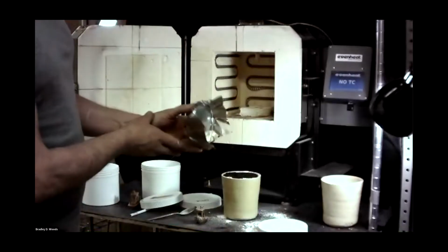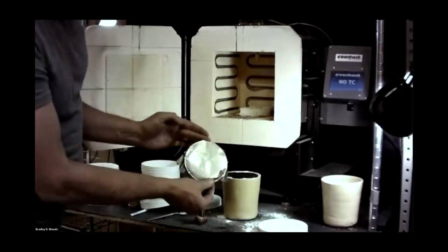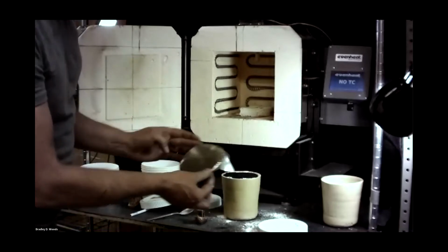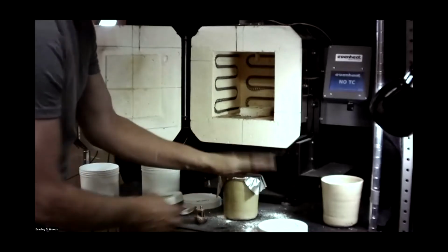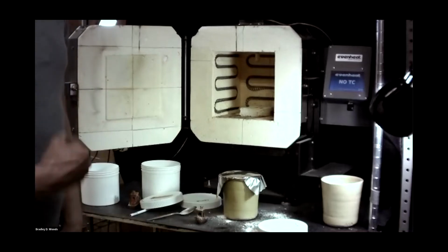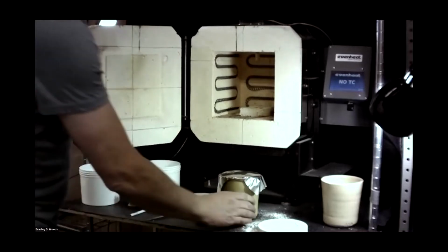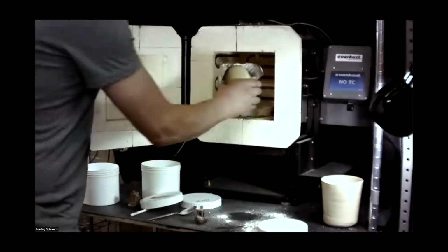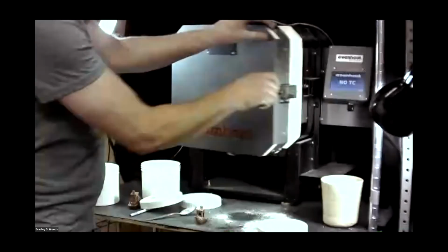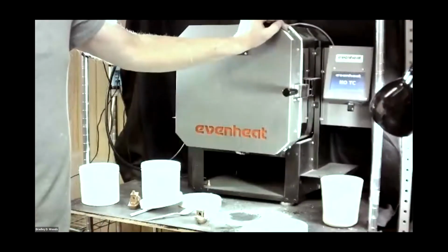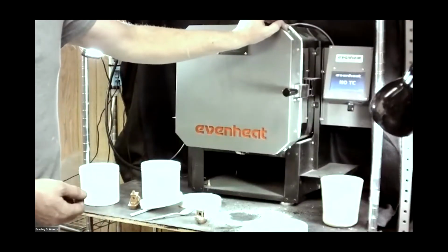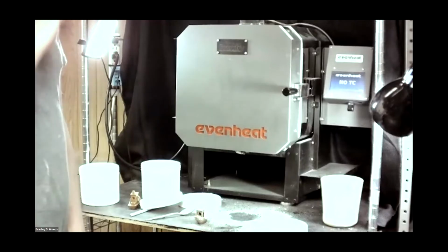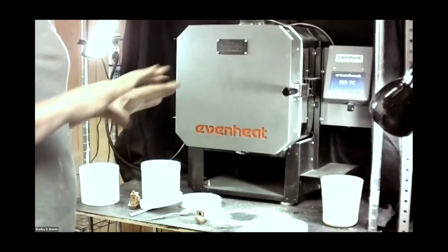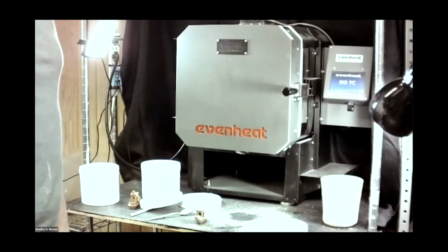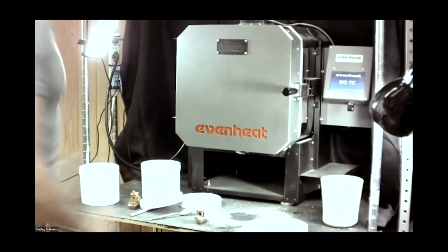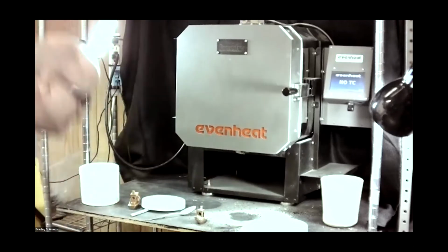There it is. Cover it. This is stainless steel foil they use for heat. They use it in heat treating a lot. So if you cover it like that, you can actually use almost no carbon, and you can sinter it back out at the end. So we put it back in the kiln for the sintering process, and this is similar. We ramp at a rate of 200 degrees per hour up to the sintering temperature. And that's it. There are no ramp and hold, none of that. We've simplified the process dramatically. Clean up a little bit here.